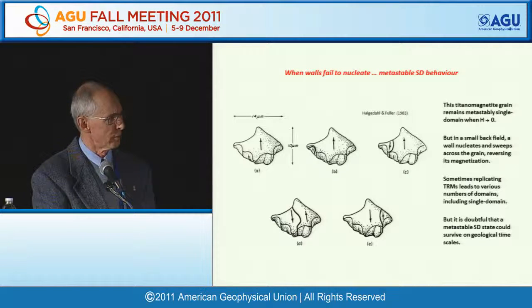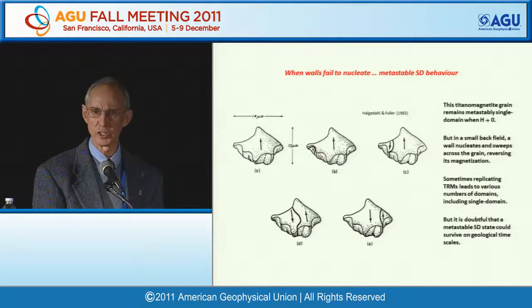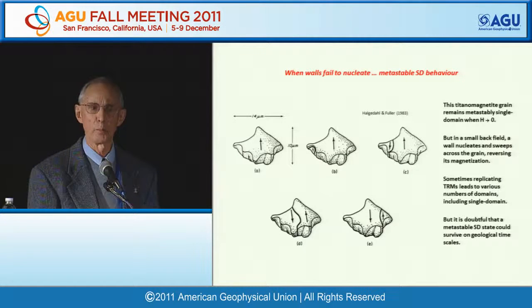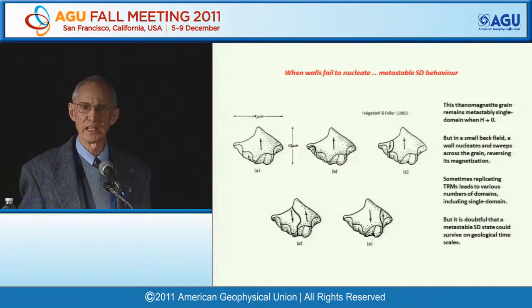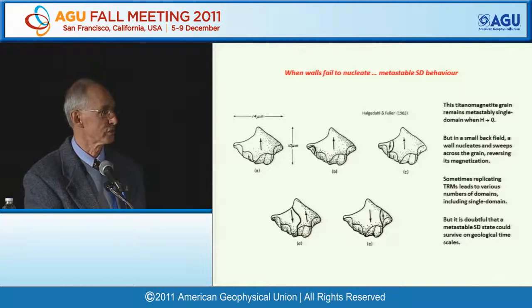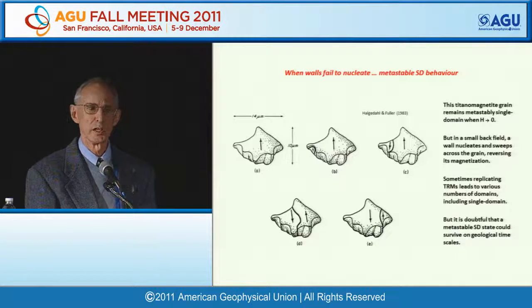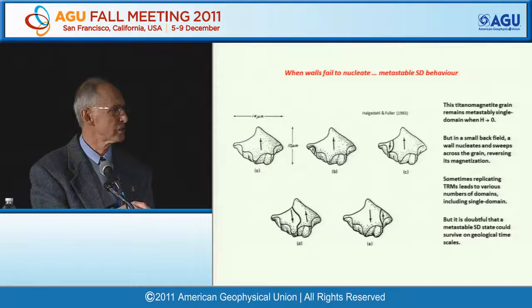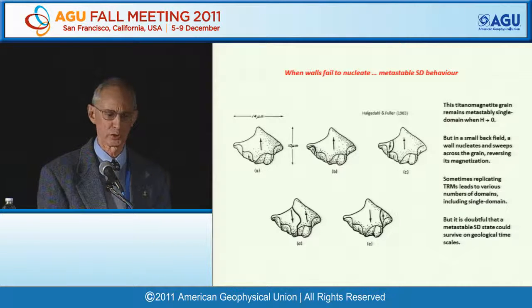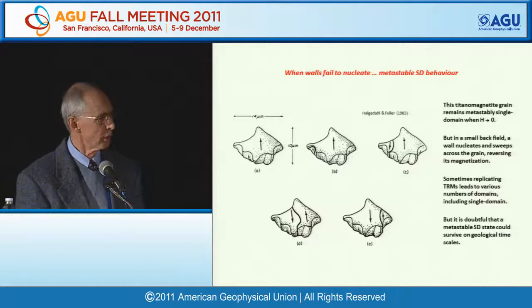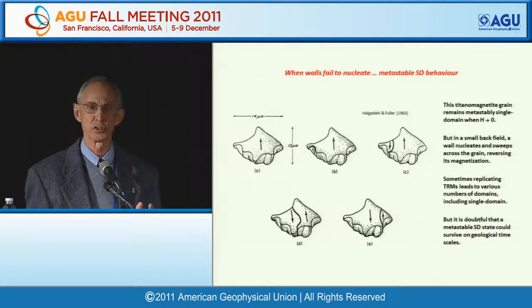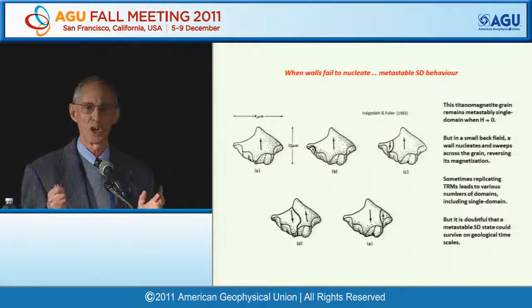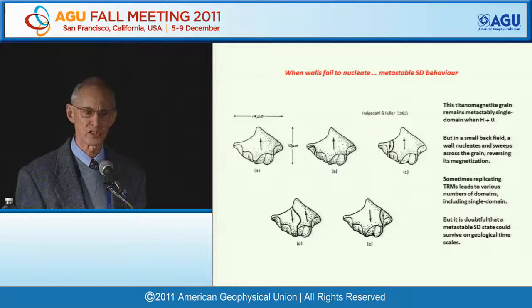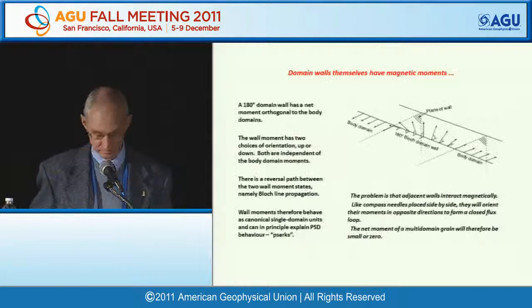In a different experiment, by simply replicating TRMs, sometimes you get different numbers of domains, including, occasionally, single domain states. The trouble, though, is that these things would have to last for geological time, and that seems rather unlikely because it's just too easy to renucleate these domains. They have strong magnetism, but they do not have very stable magnetism.